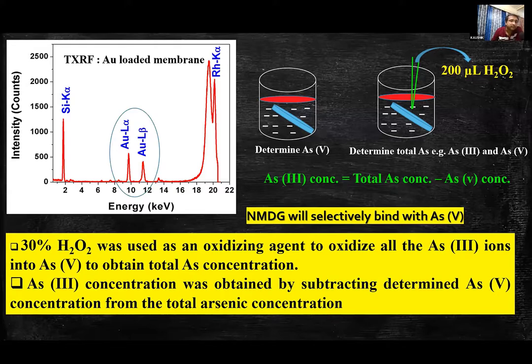First of all, I determined the arsenic 5 concentration by simply dipping this NMDG immobilized quartz sample support into the unknown solution. After determining the arsenic 5 concentration, I took another solution, the same solution. But in that case, as the solution contains both arsenic 3 as well as arsenic 5, I used 200 microliter of H2O2. Under the studied condition, all the arsenic 3 present in the solution will be converted into arsenic 5. So now whatever arsenic is present in that solution will be in the form of arsenic 5, and I determined the total arsenic concentration.